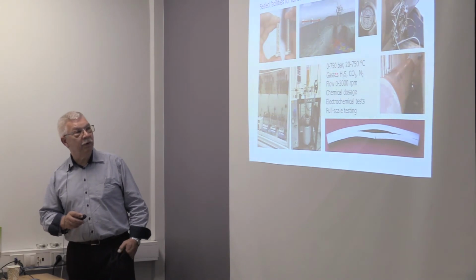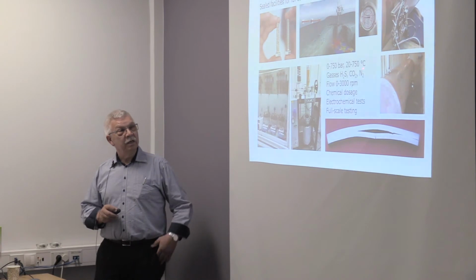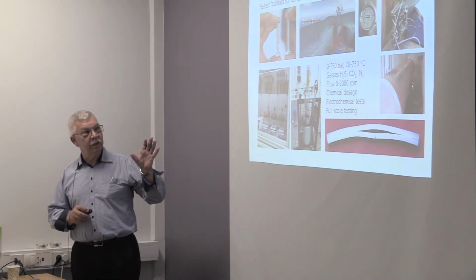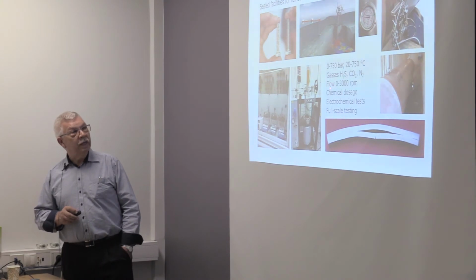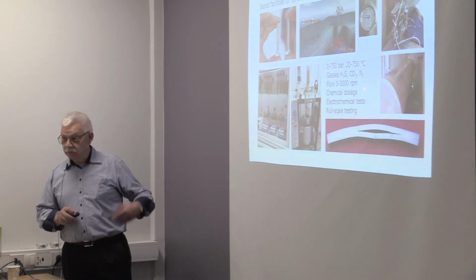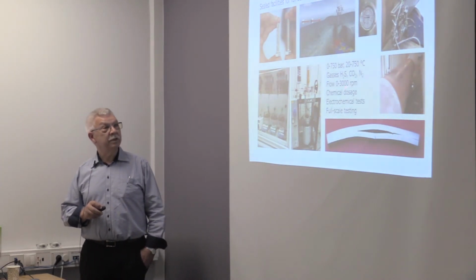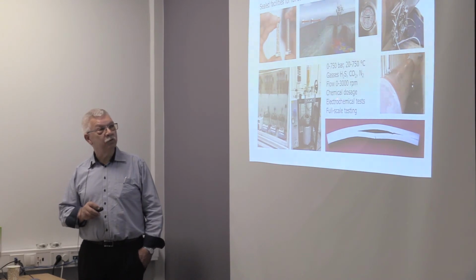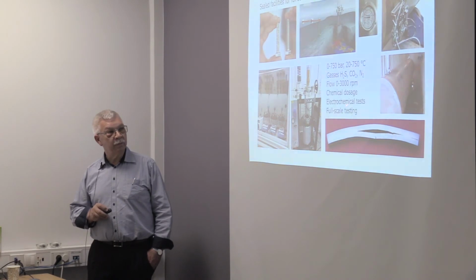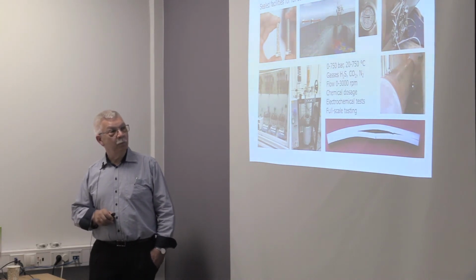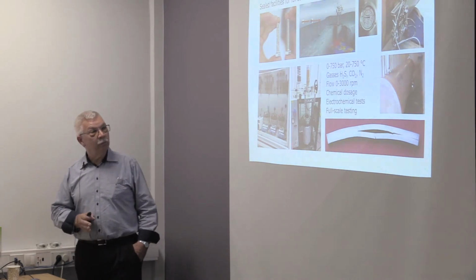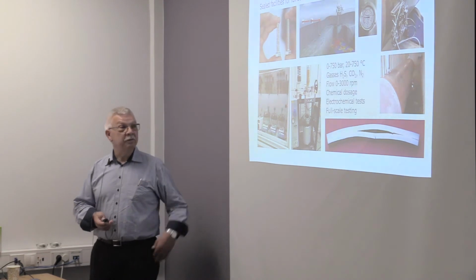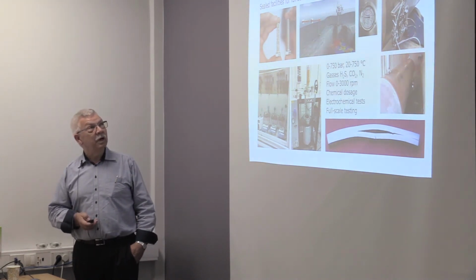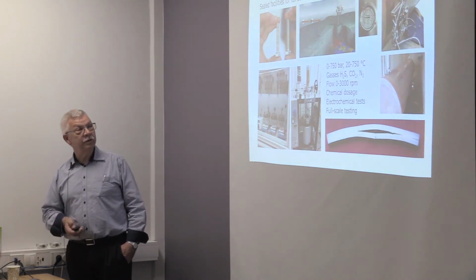We can go to 750 bars, 750 degrees Celsius. I'm not quite sure. It's the highest in gases and lower in solutions. We can handle H2S, CO2. Those were the ones considered in the Icelandic work. Nitrogen. We can have high flows. We can add chemicals, and we can do electrochemical tests under these conditions, and as I said, full-scale tests. So we would be able to help out if you want to test solutions for these very harsh environments where we have high temperatures, high pressure, and perhaps a very corrosive environment.